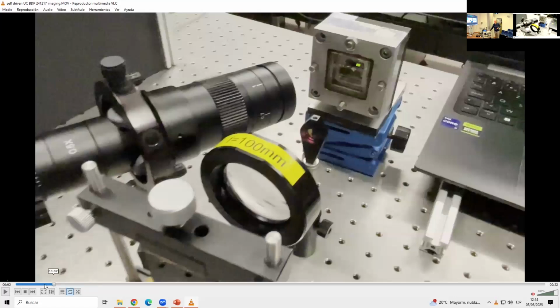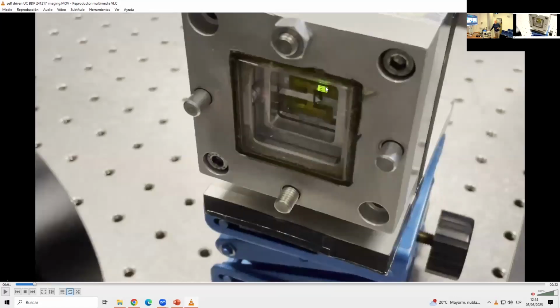So, what I wanted to show you, does this thing even have applications? Here's that pixel. It's 1 pixel, and so the electrodes are overlapping, it's about 2 by 3 millimeter, that size. But you can immediately project the image onto it, and because the conductivity in plane of all these layers is not too high, the image is kept, so the image stays. That's basically what I wanted to show here. It will become more clear, but then you know a bit where to look by this introduction. So you see some image there.